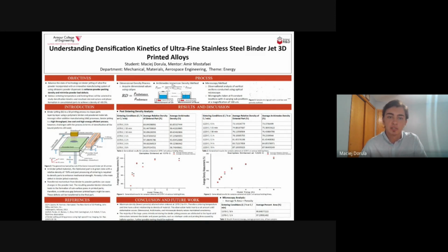Post-processing of sintering is required to densify parts to enhance mechanical strength, so the cubical samples are sintered at 1370 C at 7 different holding times, at intervals including 0 hours, 15 minutes, 30 minutes, 1 hour, 2 hours, 4 hours, and 8 hours, as shown in Tables 1 and 2. Holding time corresponds to the maximum temperature reading the sintering oven detects being held at that time for a specifically programmed time slot.